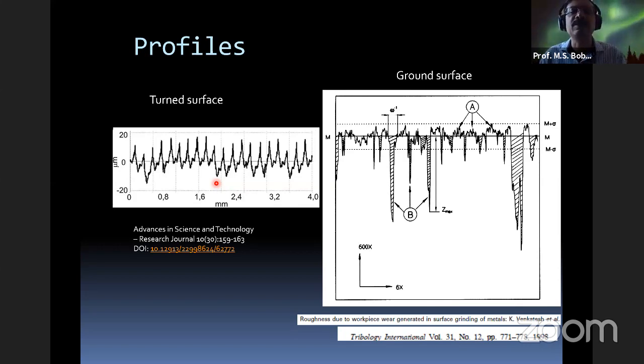When we see it with the naked eye, it looks very, very smooth. This, for example, on the right-hand side is the ground surface. And the same vertical to horizontal magnification I have plotted, but the scale is different. It's not 40 micron. So grinding surfaces are very smooth, but grinding produces deeper valleys than peaks, whereas turning produces sharper peaks than deeper valleys. There is a difference between the turning and grinding surface. Sometimes each one has its own advantages. And all these things do not get captured by the roughness profile measurement, which we are going to discuss a couple of slides later.